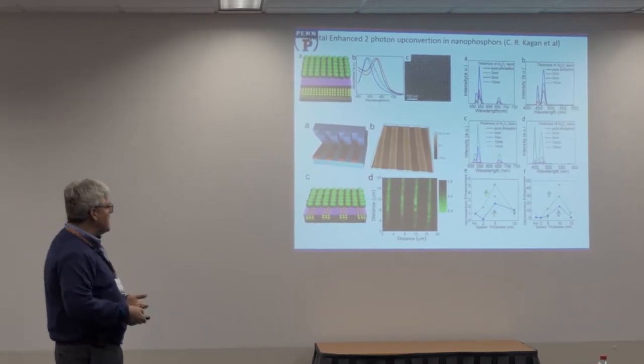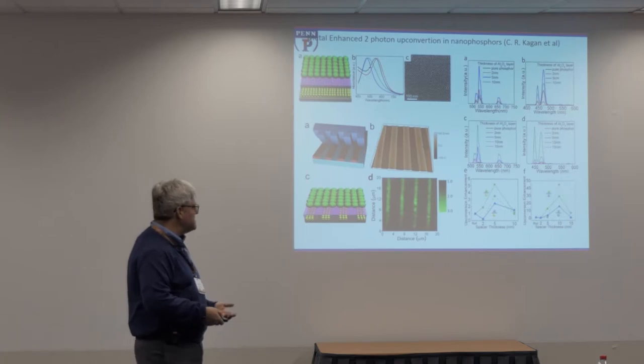efficiency. So theory would predict that in some systems it might be possible to get hundreds or even thousands of times enhancement in optical properties. Since you can only have a quantum yield of 1, that really is only relevant if it starts out really bad to begin with, right? So that is a little bit of an issue when you think about these systems, is that you're still limited by the overall efficiency in terms of quantum yield or changes in lifetime.